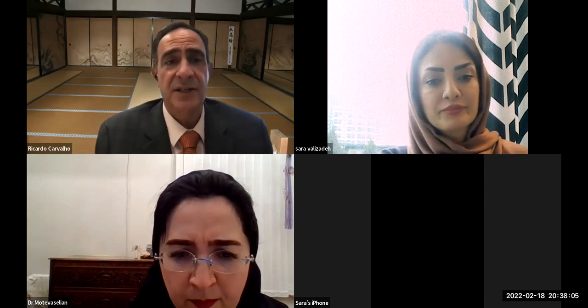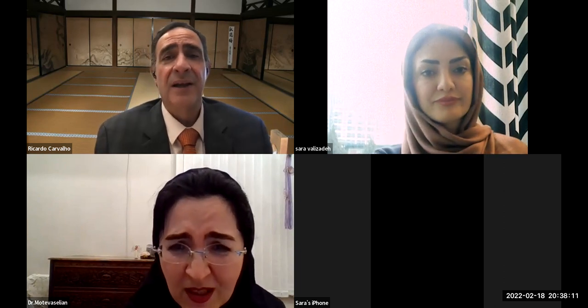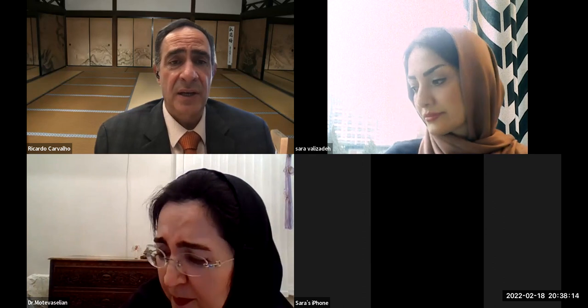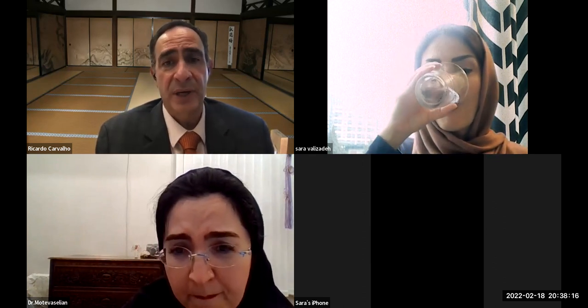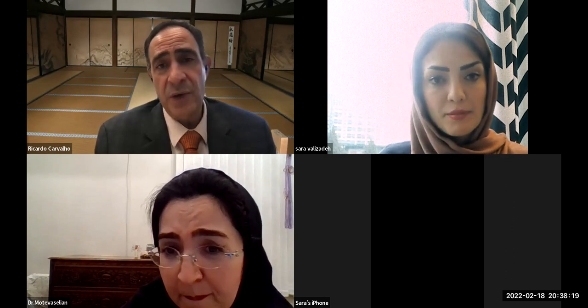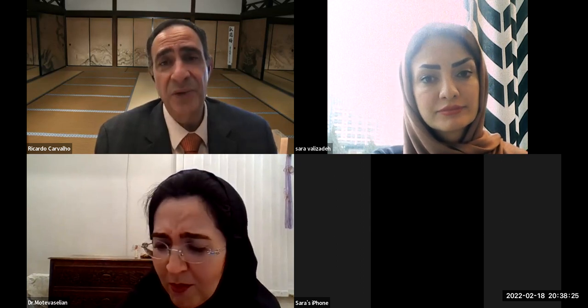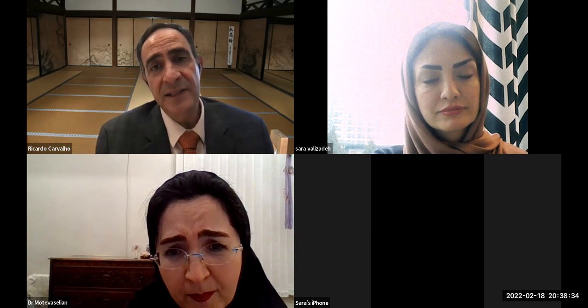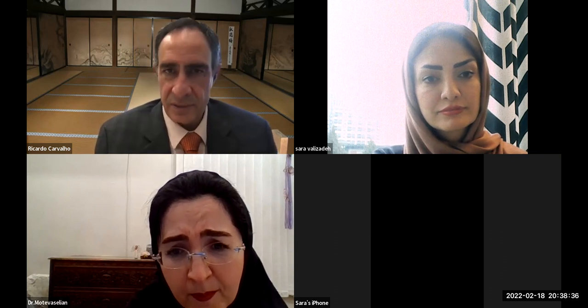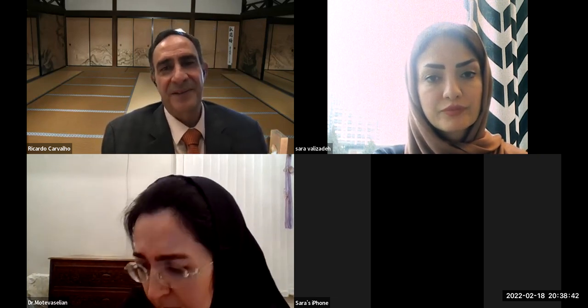But of course, this is clinically not very practical, right? So what people do once they eventually realize, wow, I'm sorry, I applied too much silane, the easiest way is to use a bur, just grab your bur and slightly remove the layer of silane. So mechanically, you can remove everything. And if you ever have to do that, then you have to start over. You etch with hydrofluoric acid again, you silanate again. And that's why silane is very important.